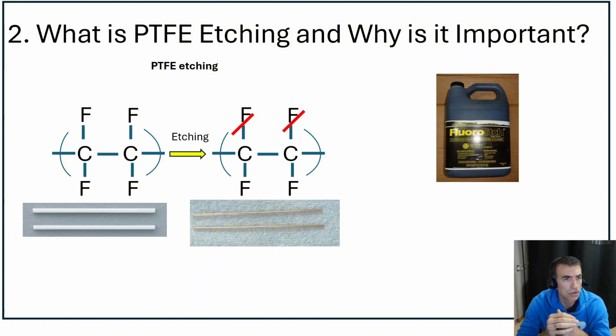They can react with other materials, and if you apply a primer, the primer would replace the fluorine. Basically, it would react with the radical and put a functional group there. If not, if you just leave the etched material in the environment, it could react with the oxygen or moisture because the radicals are very reactive. Also, the color changes when you etch it; it becomes more brownish. In analytical polymers, we can identify and quantify the etching, and say, okay, this part has been 30%, 60%, or 100% etched versus a reference sample.